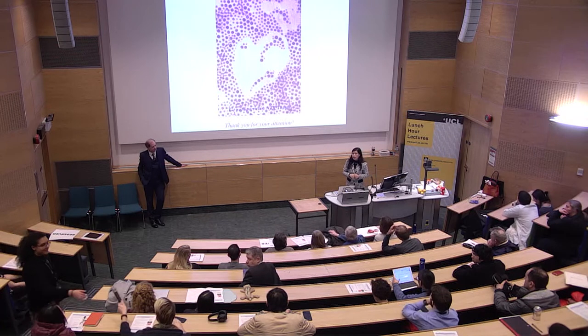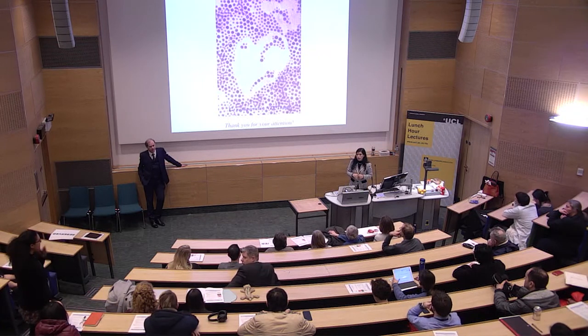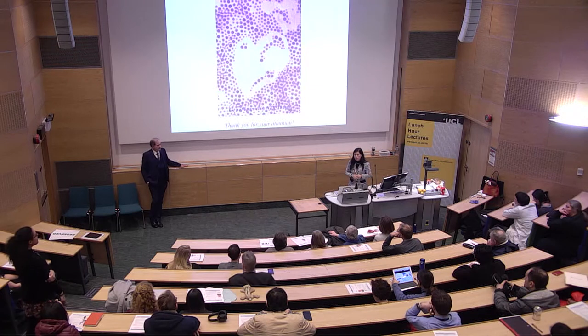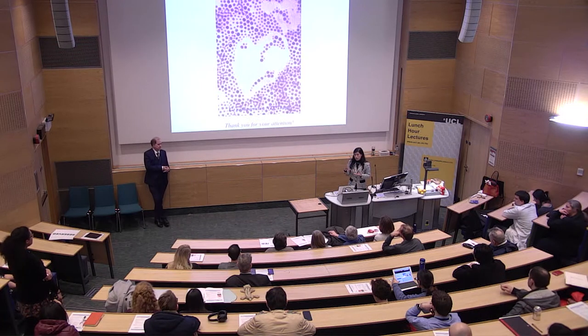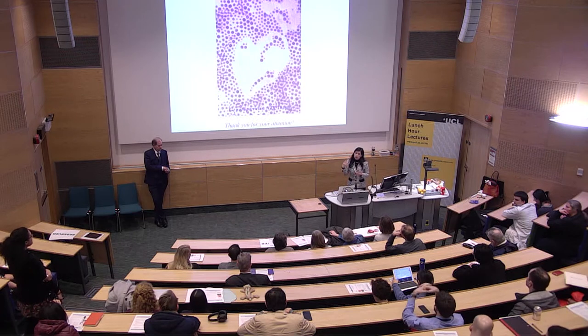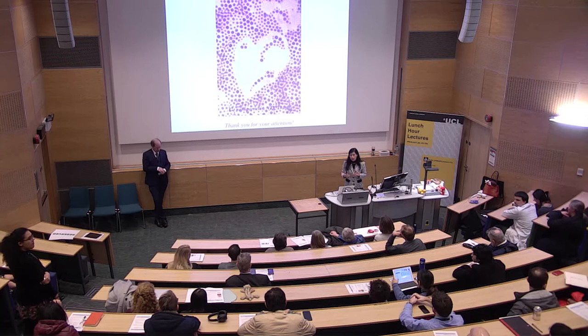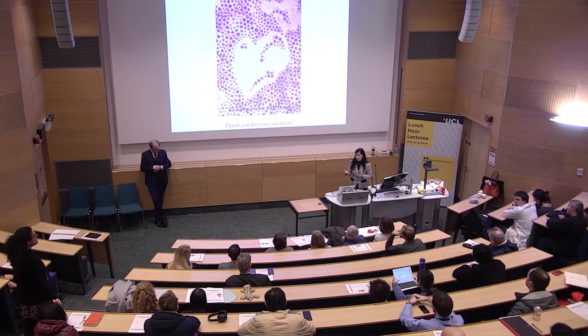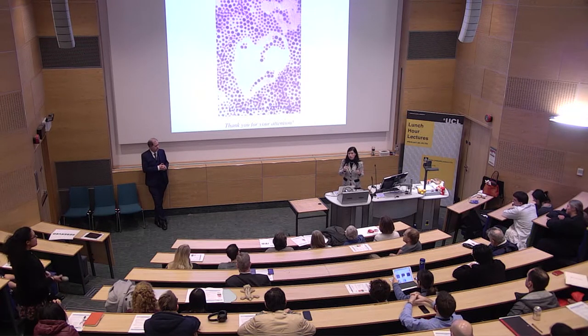Yeah, I think that is a very good question. And I think that we all have to take care of that when it happens. That means you have to control the dose. And not only the dose as in the concentration of the particle, more importantly it is a heat dose. That means what type of nanoparticle, what size, what chemical composition, and also, more complicatedly, you have to use an alternating magnetic field. So different field and different frequency, you will have a different heat dose.